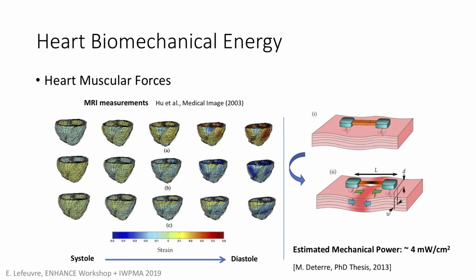The other approach was to say, okay, we have a lot of muscular force, and if we use this kind of device with 2 anchors, let's say 1 centimeter distance from one to the other, when the muscle contracts, if we put a transducer here, we can convert energy. Based on a lot of data that we also found in literature, we estimated that it could be possible to harvest about 4 milliwatt per square centimeter. So it looks very interesting.